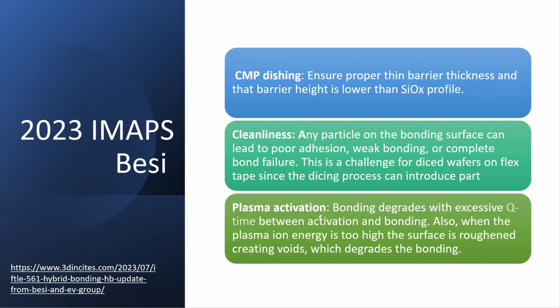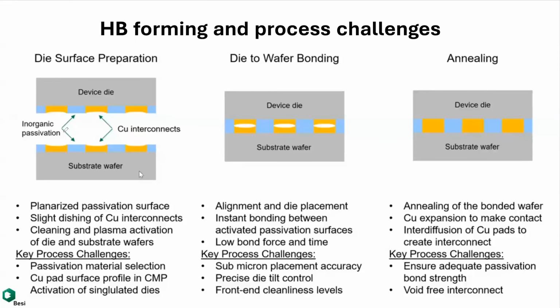Okay. The plasma activation, the bonding, they found out you need to, as I show in here, passivate the surface first. You have to passivate especially this inorganic material, SiO2, in such a way that the surface forms some kind of hydrophilic bonding to help you bond. So, hydrophilic surfaces, so you can help the bonding.